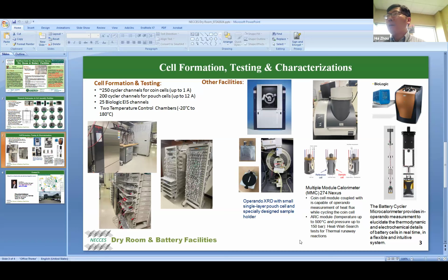Because our present project does a lot of thermal studies, we have some equipment to do some operando thermal monitoring, to check either the coin cell or the pouch cell, what heat release is produced during the charge process. And for this module, we also have the ARC modules that can check the self-heating rate and also monitor the thermal runaway reactions, which can go up to a temperature of about 500 degrees Celsius and pressure up to 150 bar.